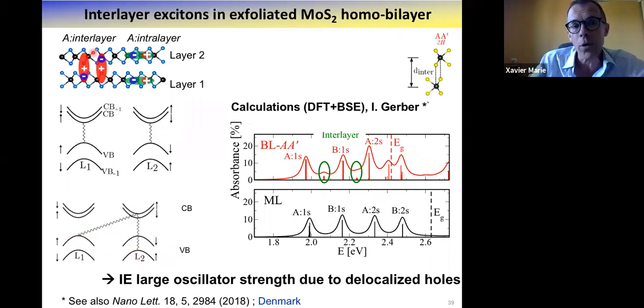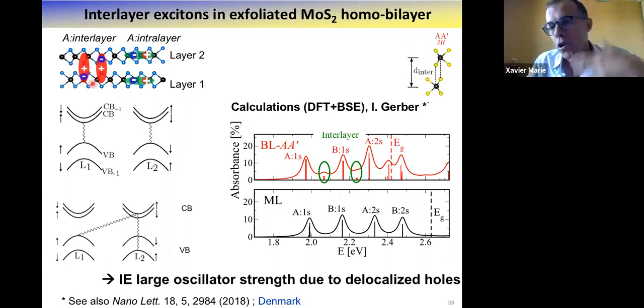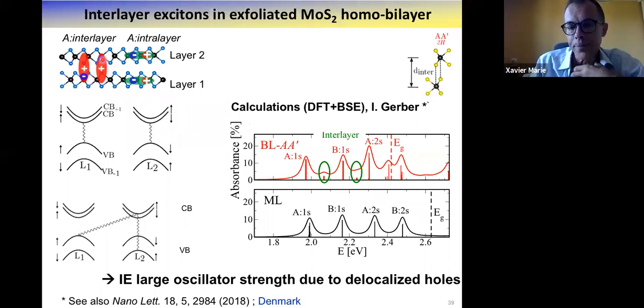So a good way to represent this interlayer exciton is shown here, where basically the hole will be delocalized over the two layers, whereas the electron will be localized either on the top layer here or on the down layer here. If you don't apply an electric field, these two excitons will have the same energy, but we will see later that by applying an electric field in particular, we'll be able to lift this degeneracy.